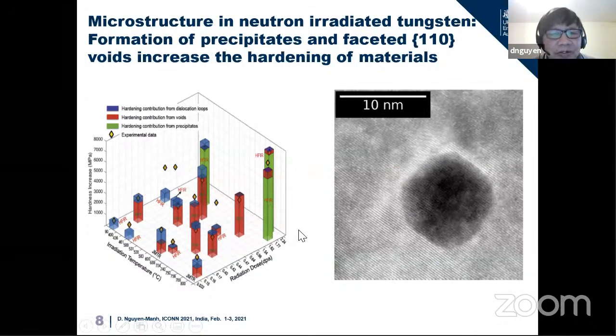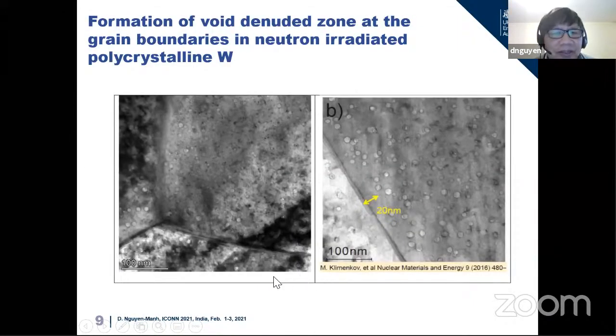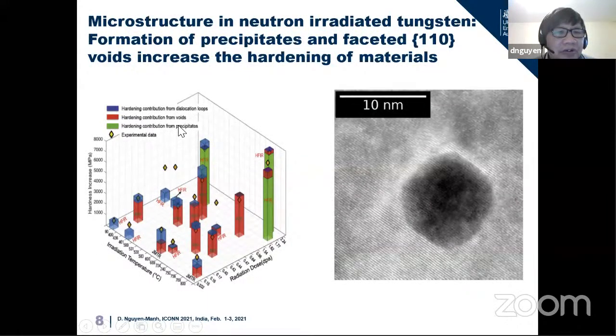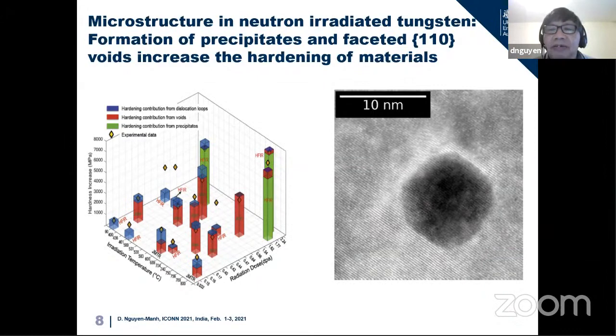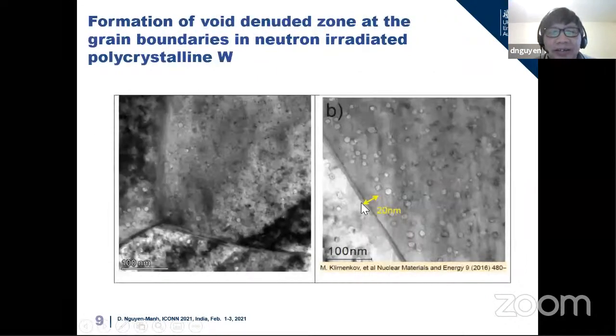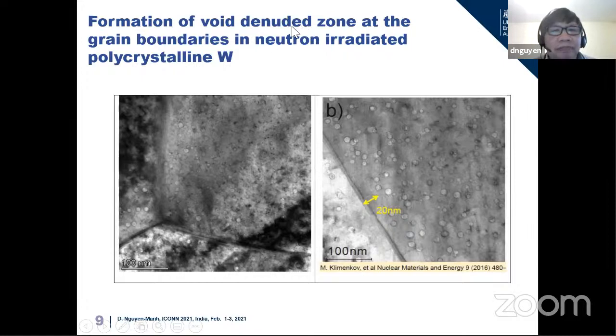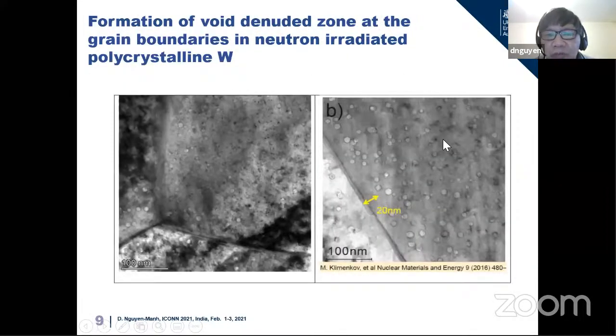The key consequence of these defects is the contribution of voids and the contribution of the precipitates to the hardening of the material, which is really important at high temperature. So it is important to understand the origin of the precipitate and the nature of the void forming in tungsten under neutron irradiation. If you have a polycrystalline sample, then you can see that the voids are in a so-called denuded zone, away from the grain boundary. That is a phenomenon we also want to understand, why it's happening, if possible from ab initio calculation. So it is a very large scale, engineering scale.